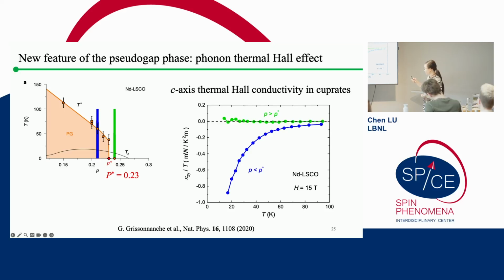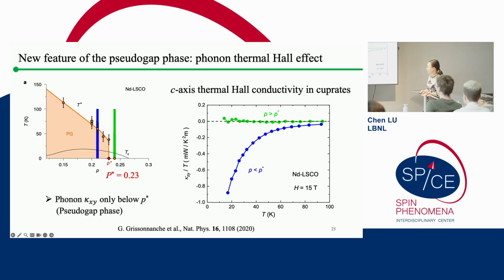And what we found is for this c-axis thermal Hall conductivity, if you take a look at this green curve, outside the pseudogap phase, the signal was 0. However, if you go below the critical doping, which is the blue curve, when you're sitting inside the pseudogap phase, you see a non-zero, negative, very large thermal Hall conductivity signal actually coming from the phonons. So this result reveals a new feature of the pseudogap phase: a phonon-driven thermal Hall effect that only exists below p star. And the exact mechanism behind that still remains an open question.